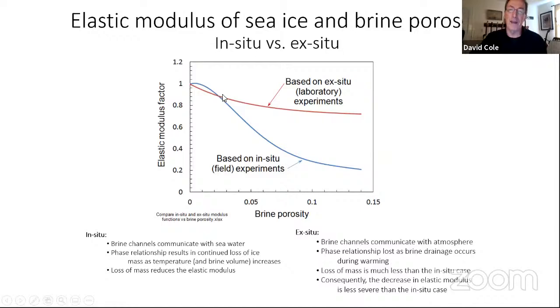You would then apply this factor to get at what the brine porosity effects would be on the pure unrelaxed elastic modulus. When we started taking a careful look at our in situ results over a fairly broad range of brine porosities, we found a much, much lower modulus. This is a factor of almost 4 out here at brine porosities associated with in situ, kind of warm ice temperatures.